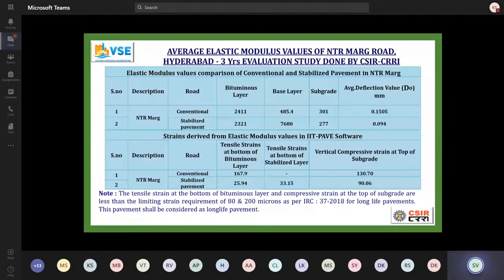At the bottom, if you see the tensile strain at the bottom of the bituminous layer and the compressive strain at the top of subgrade, they are less than the limiting strain requirement of 80 and 200 microns as per IRC 37 for long life pavements. The tensile strain for the stabilized pavement was around 25 or 26, tensile strain was around 30, and the vertical compressive strain at top of subgrade was around 90, which is well within the norms or even less. This is after 3 years, so it gives you an idea of how good the layer is.